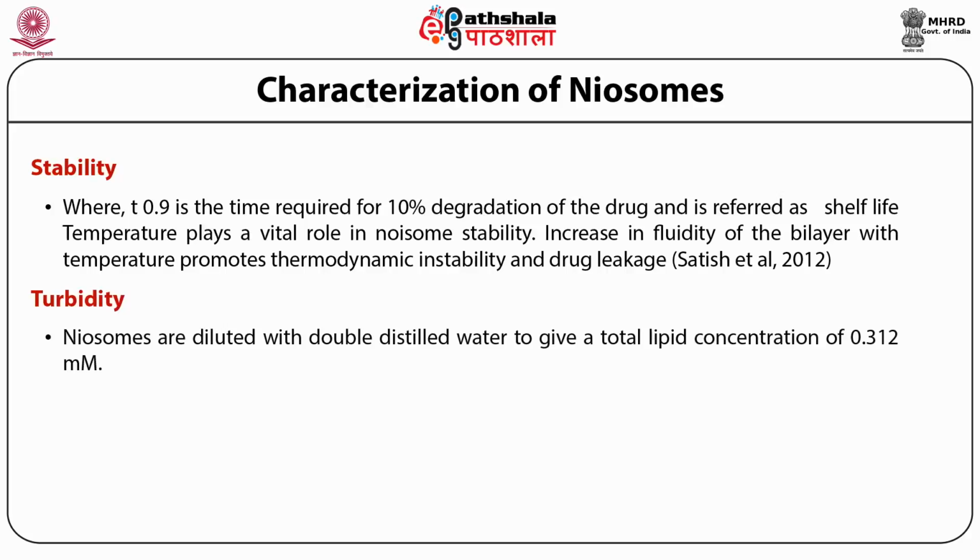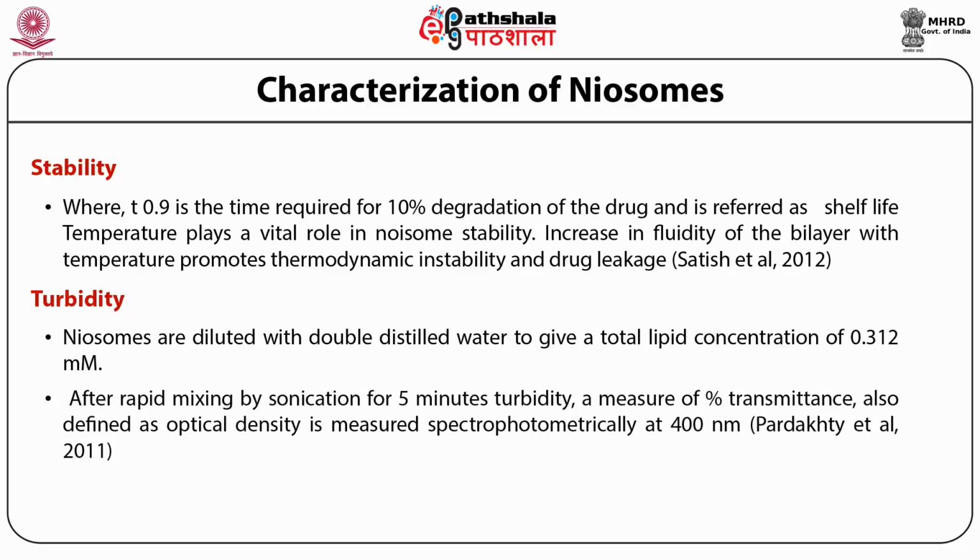The niosomes are diluted with double distilled water to give a total lipid concentration of 0.312 millimolar. After rapid mixing by sonication for 5 minutes, turbidity, which is a measure of percent transmittance and is also defined as optical density, is measured using a spectrophotometer at 400 nm.